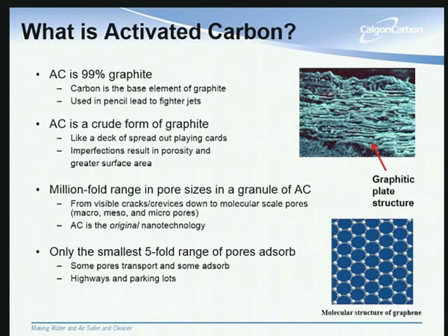In fact, you can find up to 1 million-fold ranges in size as far as the pores go, all the way from visible cracks and granules down to the microscopic. The old timers back at Calgon Carbon like to argue that activated carbon is the original nanotech. I'm not sure that I agree with them on that point, but I get where they're coming from. However, when it comes to adsorption, it's really only the smallest 5-fold range of pore sizes that do the adsorption. Okay.